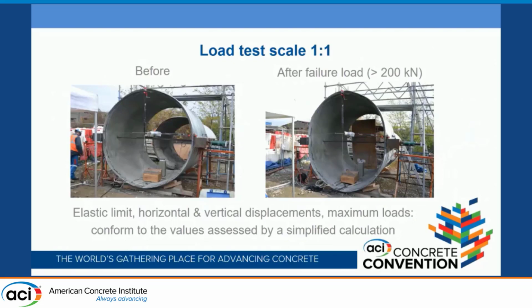So you can see on the left the test body before loading, and on the right, the test body after loading. The failure load reached 200 kilonewtons, which was the expected value. As for the failure load, the yield strength and displacement were found to be in accordance with the simplified calculation.